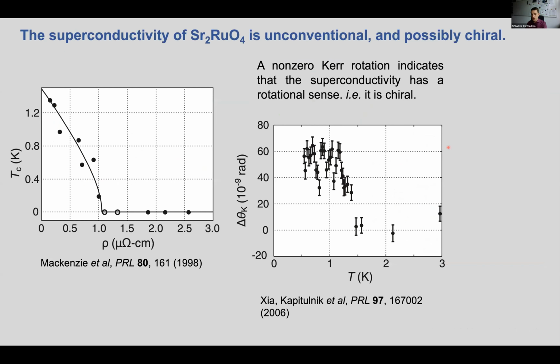Okay, so now I want to talk about the superconductivity. Strontium ruthenate, as I've told you already, is a superconductor, and it's very clearly an unconventional superconductor. Its Tc is extremely sensitive to the residual resistivity. A very small concentration of defects suppresses the superconductivity completely. That means it is an unconventional superconductor.